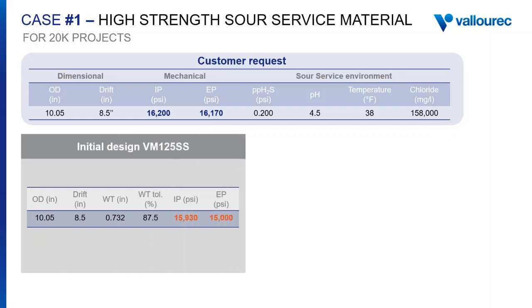The customer's original well design included the VM125SS, a sour service grade with a specified minimum yield strength of 125 ksi that has been qualified for this region 2 condition. However, this product could not meet the mechanical requirements, being well below both the internal and external pressure needs. As mentioned before, the only alternative seemed to be to increase the wall thickness, but this was not possible due to the very tight tolerances for the OD and the drift.